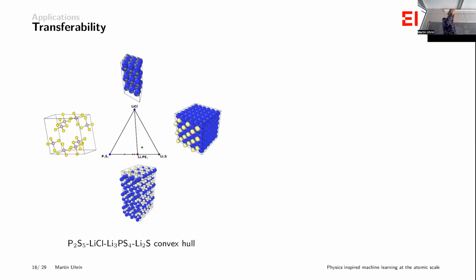Now, the reason that surprised me is because if you imagine what the machine learning model is really doing, it just sits on an atom, looks around it, looks at where the other atoms are, and says, okay, I think the energy of this thing should be this. If it's never seen a configuration like this one or this one, which it won't have because we're in a crystal structure that has a different stoichiometry, different local environments, it shouldn't be able to correctly guess the energy of these. And yet, in the end, it did a totally fine job.